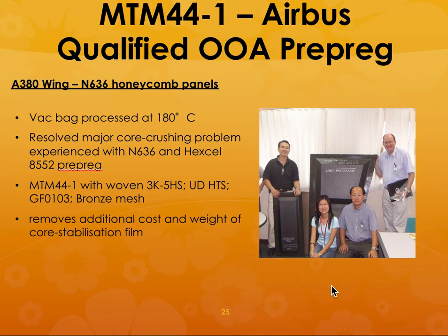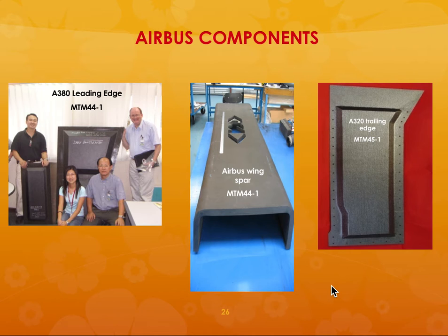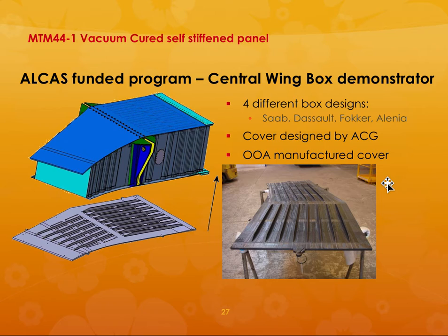So these have been qualified and are being used by a number of manufacturers, like in this case Airbus. So you can see that they are qualified. In this case, it is the Airbus wing spar, and in this case, it's a trailing edge. So these were made using out of autoclave prepreg type of material. So this was a demonstrator for Saab and Fokker, and these are made using these materials, made outside the autoclave. So this was a demonstration part, but what they found is that it would have the same kind of properties as the parts made using standard prepreg materials that are autoclaved.